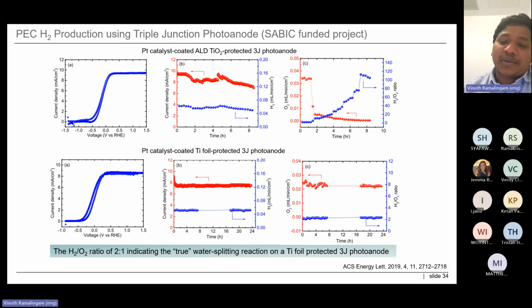What I'm trying to say here is, even with the protection layer, people think that the photoelectrodes are stable to perform the reaction, but it's not. You need to really monitor the oxygen evolution reaction in parallel to understand this is really a water splitting reaction. Otherwise, this is just photocorrosion. That means the photoelectrode undergoes degradation, the photooxidation and photocorrosion will happen. In that case, you will see the current density stable, but it's not from the water splitting reaction. That's just coming from the photocorrosion of your photoelectrodes.